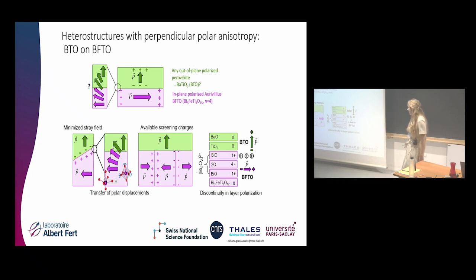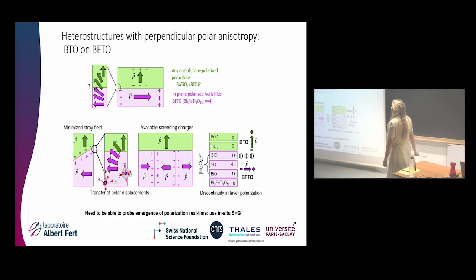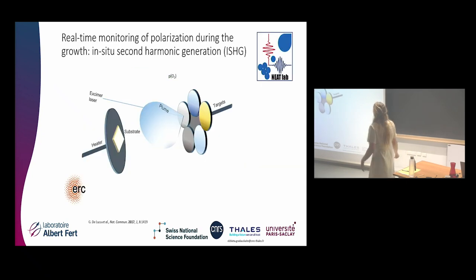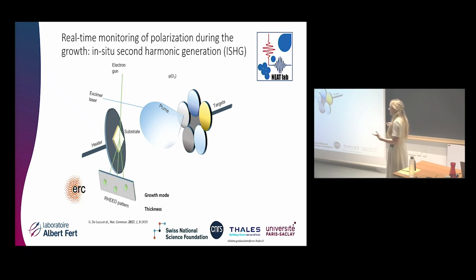And how can we probe it? To really see what is happening, we're using optical second harmonic generation during the growth, and we can look at what is happening at this interface. So just to show you a bit, that's how I grow my PLD samples. As per usual, we have RHEED, so electron diffraction, to monitor unit cell by unit cell growth in thickness, and to know the growth mode.